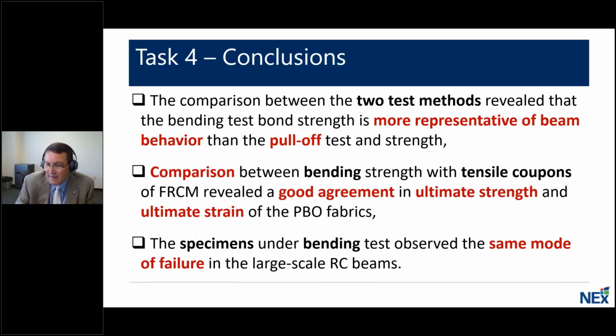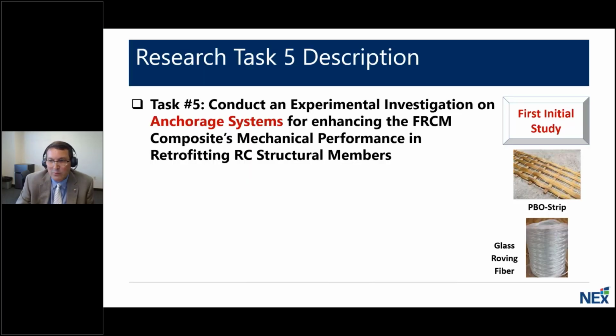In the pull-off test, the pull-off load was applied perpendicular to the PBO fabric alignment, as you saw, whereas the bending test applies load parallel to the PBO fabric alignment. That concluded that the observed higher strength in the FRCM composite was in the bending test rather than the pull-off test itself. Finally, we'll move into the last task, which was looking at anchorage systems.